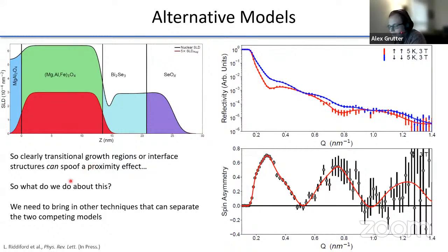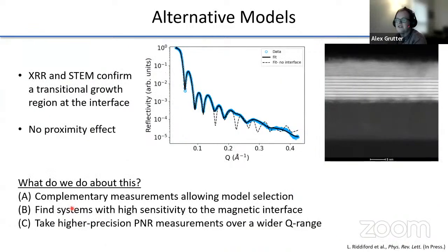And so, how do we separate these two competing models that give us basically the same neutron reflectivity fit? We need to bring in other techniques to separate the two competing models. And so what we did is X-ray reflectivity and transmission electron microscopy, both of which confirm a transitional growth region at the interface and have no proximity effect.